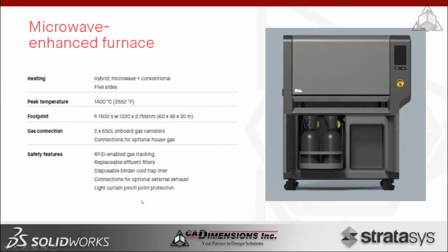After the part is printed and comes off the machine, the next step is a debinder solution. That is very similar to a wash tank, if any of you use a Stratasys FDM system, where we have an agitation bath and a chemical compound in that solution. It's going to start to remove some of that binder and some of that ceramic spacer in the part. The part is going to reside in that solution for a couple of hours, and then it's going to make its way into the furnace. The furnace here, you can see, is the picture on the right. It's a hybrid, so it uses both conventional and microwave frequencies to heat up the oven to 1400 degrees Celsius. It does use argon gas during this process, and those canisters are housed in the bottom of the machine. The furnace is going to run anywhere from 16 to 24 hours based on the part, material and volumes that you're printing, which is all calculated in the software.